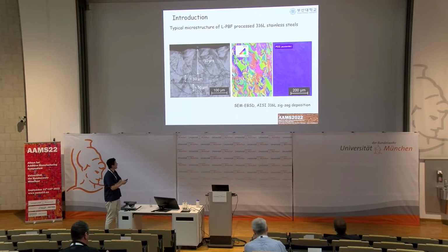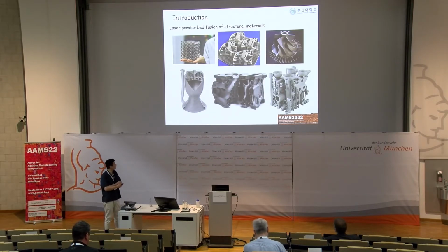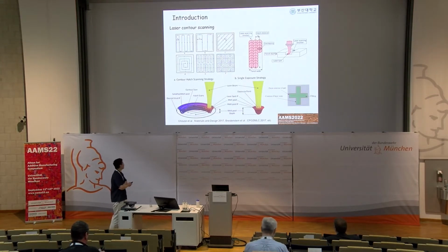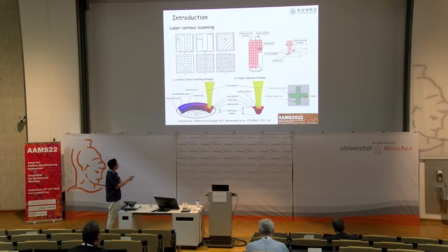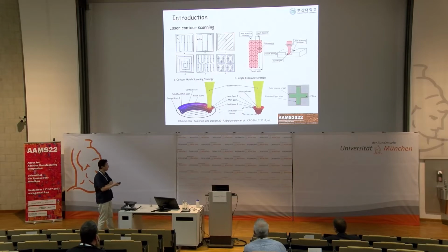But if we consider internal structures or small feature sizes, then there is one additional thing that we have to look at, which is the laser contour scanning. This is most popularly used in many commercial LPBF systems, at least those integrated with the Magics software. If we fill in one layer with a zigzag pattern, then we have some kind of stripe pattern on the surface because of the surface tension. This is bad from the point of view of surface quality. So to get rid of the stripe pattern, we usually do an additional laser scan on the outer surface so that we don't have the stripe pattern anymore.